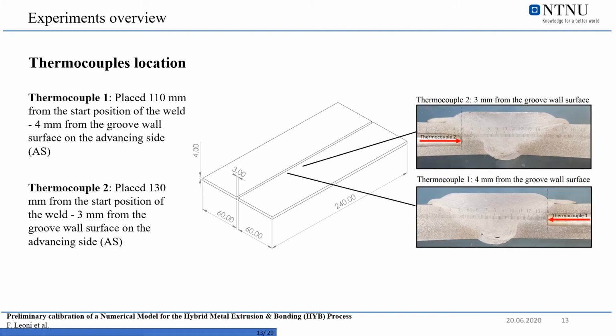As I said, two thermocouples were used. One was placed 110 millimeters far from the start position of the weld, and it was 4 millimeters far from the groove wall surface on the advancing side. The second one was 20 millimeters ahead of the other one, and it was 3 millimeters far from the groove wall surface on the advancing side too. And so this is how the temperature was measured.